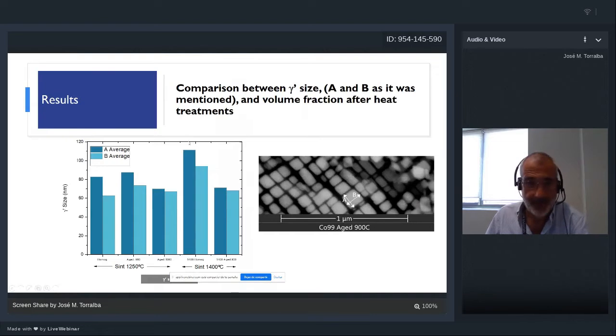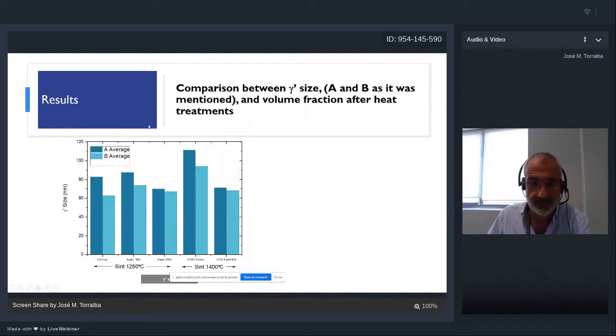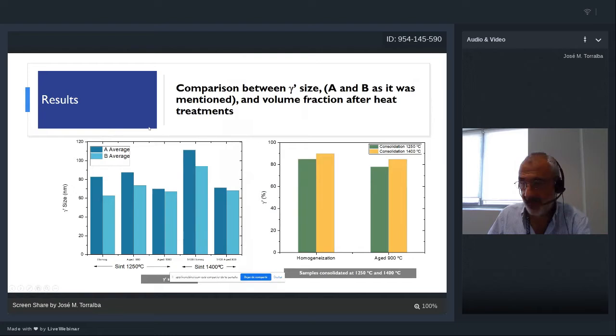So here we have the comparison between the gamma prime size in the different stages, in the material sintered at 1250 and in the material sintered at 1400 degrees. Here we have the A and the B parameters, and you see that we have maintained more or less the same level of the size of the precipitates. Only in the case of the materials homogenized at 1400 degrees, we have a higher size of the gamma prime precipitates. If we also analyze the volume fraction, we have similar volume fraction for the materials aged or homogenized, but a little bit higher for the homogenization process.